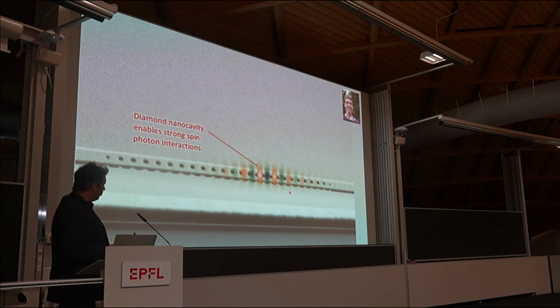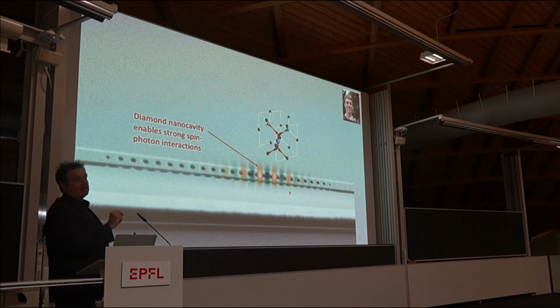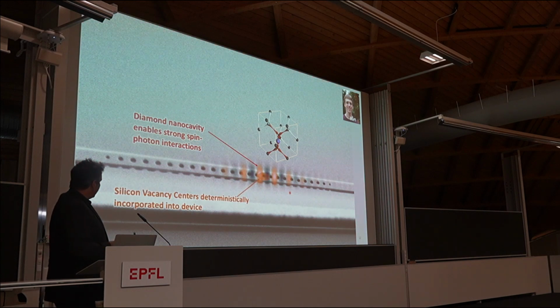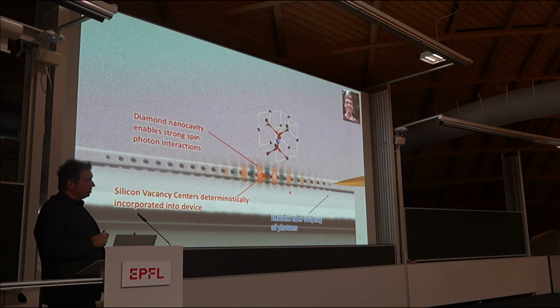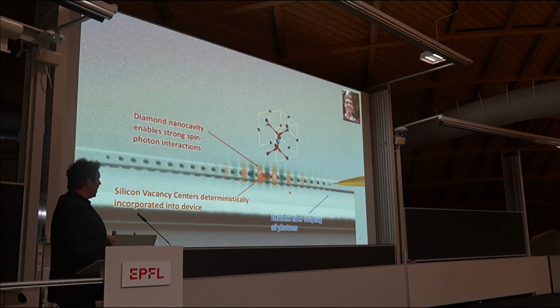After we fabricate the cavity, or before, depending on the process, we implant color centers in diamond exactly in the location of the center of the optical mode. We do this by aperture implantation with precision up to 40 nanometers in all 3 dimensions. And then basically this can be very strong coupling, very high cooperativity, which is an important figure of merit in this business, between spin and photon. And in order to talk efficiently between spin and photon, you need to have a very efficient interface between the macro world, represented by this optical fiber, and the diamond nano world, if you will, where the silicon vacancy is the center.